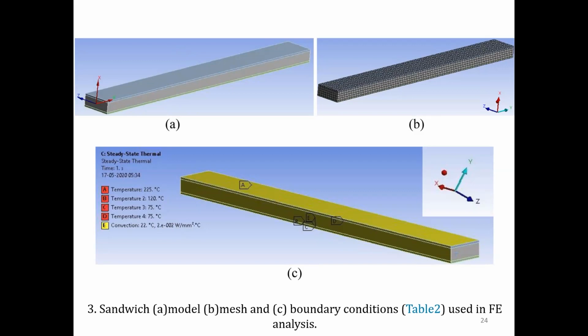Then we thought to have, as this slide shows, a finite element analysis just to look at the stress distribution across the sample. So here, the 3D printing, as we all know, involves complex heat and mass transfer phenomena that affect the dimensional accuracy of the final part because we are printing at an elevated temperature. So the thermomechanical finite element simulations are carried out using ANSYS. We had the 2020 R1 version, and suitable printing parameters, which we finalized in printing, were fed as boundary conditions to visualize only the temperature and thermal stress distribution. We didn't do elastic plastic analysis here.